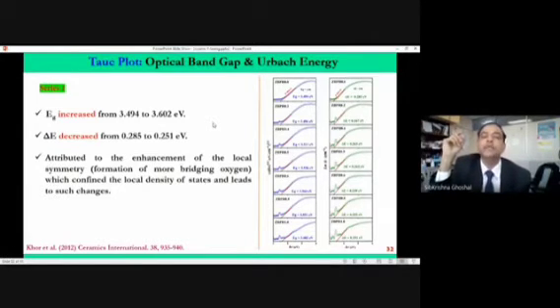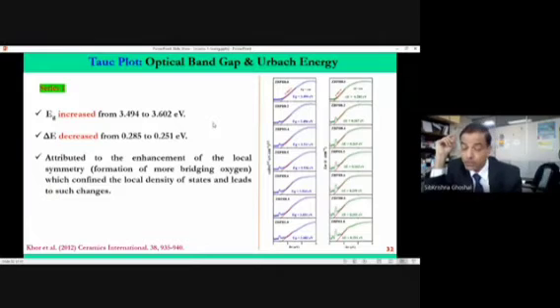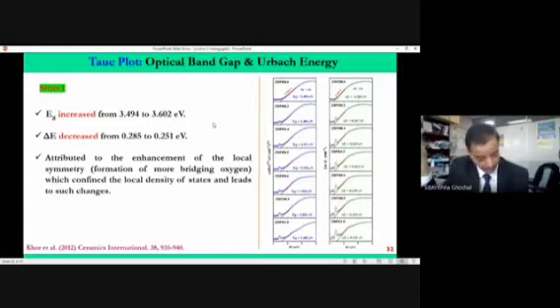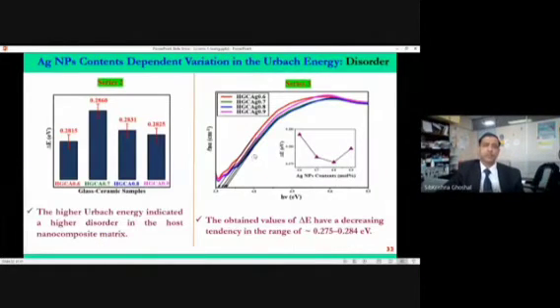And that's where glass ceramics are interesting, because you can tune the band gap over a wide region by controlling the concentration of the nanoparticles and combinations. And you can put 2 different nanoparticles, 3 different nanoparticles, 2 different rare earths, 3 different rare earths, depending on your aim. So that's the way we are trying to do. When you put the silver nanoparticle, in the presence of silver nanoparticle, the disorder changes. That's what exactly I was talking about. The local symmetry of the system changes. This local symmetry will control the optical properties, and that's where Judd-Ofelt theory comes in, and we also do Judd-Ofelt theory to compare with the results.